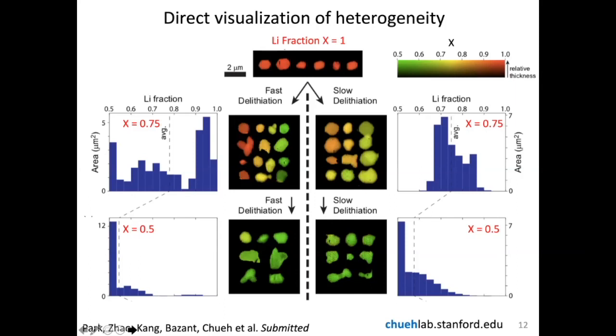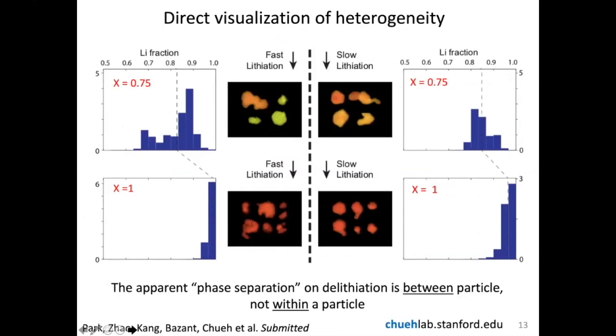But when you perform the experiment under fast charging conditions, so now we are removing lithium very quickly, you no longer see this unimodal distribution, but you see this multimodal distribution. In other words, we're finding that certain particles are full of lithium and certain particles are devoid of lithium. And this is only found when you charge very quickly. When you charge slowly, you revert back to the standard unimodal behavior. So this was very interesting because that tells us that this apparent phase separation is between particles, but not within a particle. So this directly contradicted the diffusion-limited picture, whereby we should find that all particles have very similar composition on average. So we were very puzzled by this behavior.